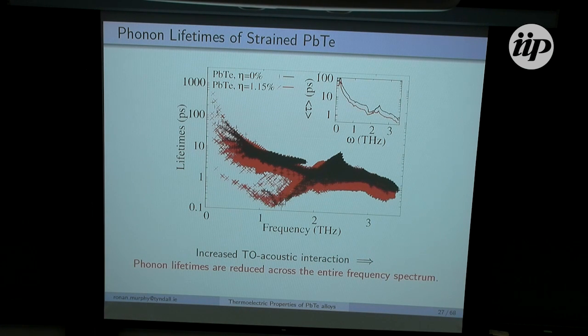And what's also quite interesting here is if we take a look in the top right, we see a little inset here of the averaged phonon lifetimes as a function of frequency. And the thing here is that this reduction in phonon lifetimes is maintained across the frequency spectrum, particularly helping to scatter those low frequency phonons.